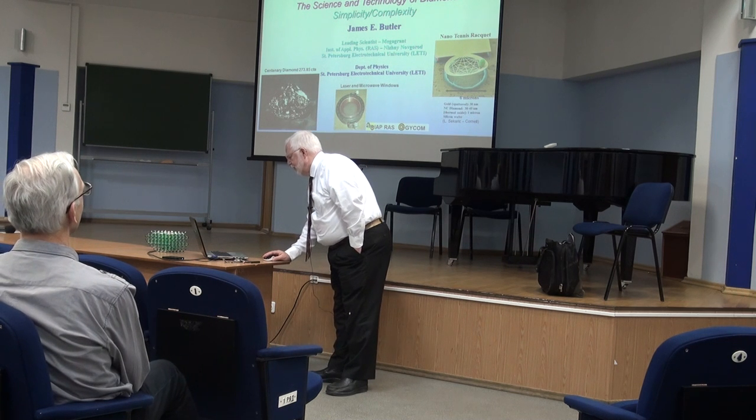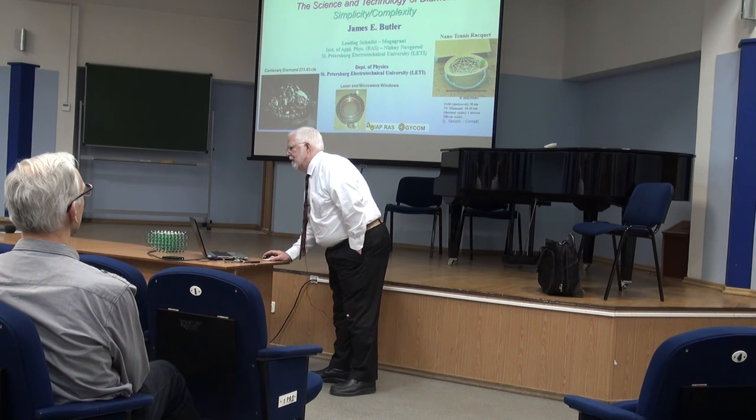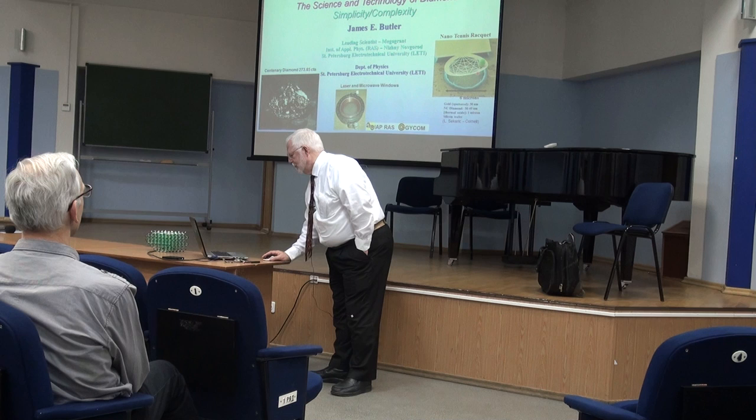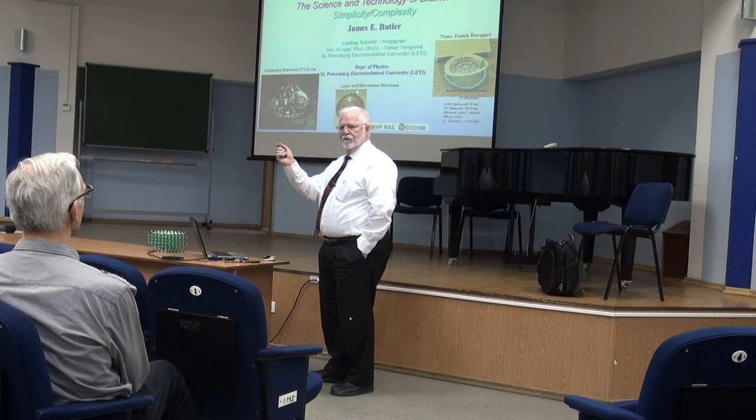And if you look very carefully, right about here, let's see if it shows there, there is a ping pong ball. It's a 100 nanometer diameter particle, dust particle. And you can see that these diamond films have no cracks in them, even though they're only 30 nanometers thick.